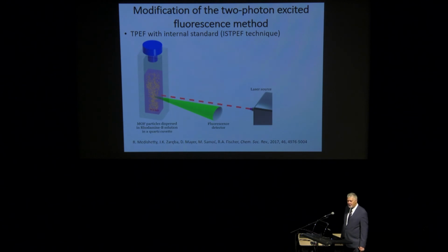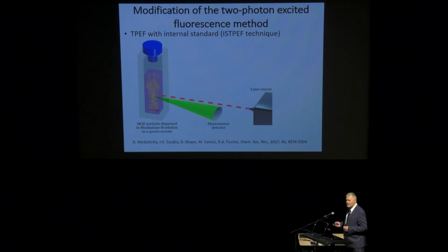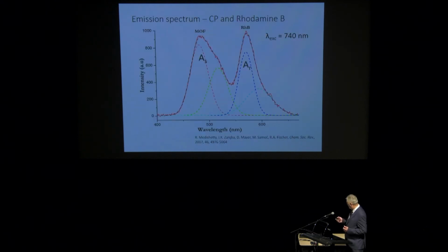Okay, how do we determine the values of the parameters which characterize these things? Because we need to have that. We need to compare molecules with crystals, with powders. So yes, we actually discussed several of these techniques. There's one of the techniques that we use, the internal standard technique, in which we compare the components of the spectra coming from the MOF with the component of the spectrum coming from the luminescent dye, and then we can calculate the cross sections of the involved species.